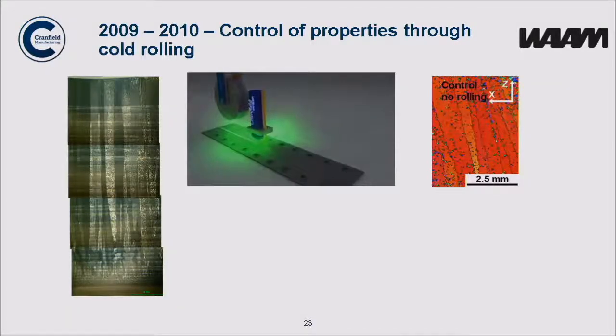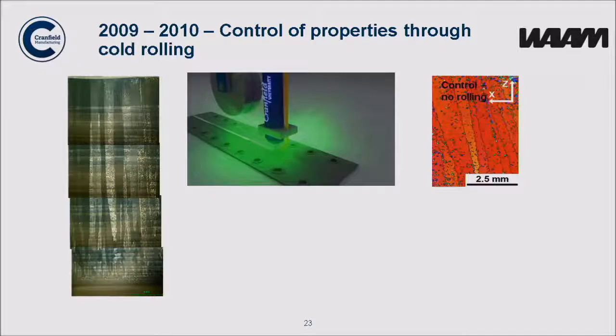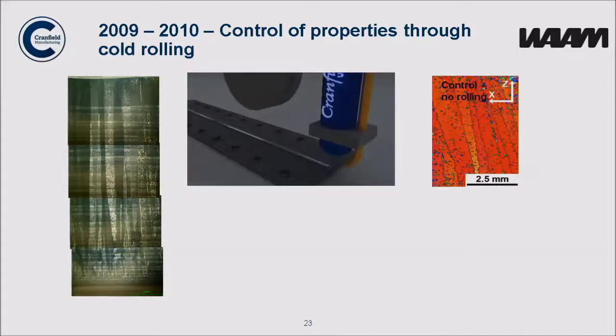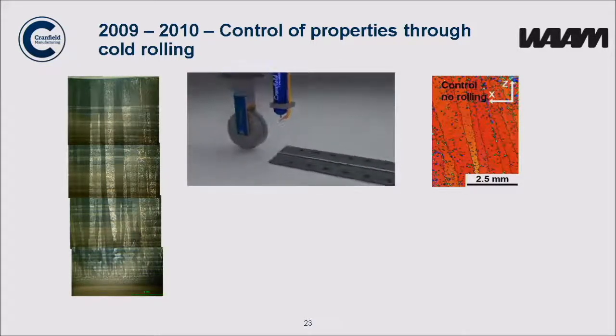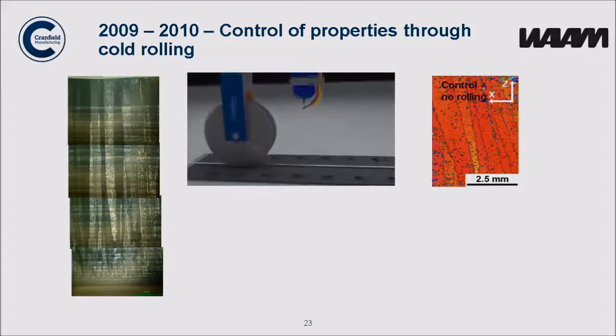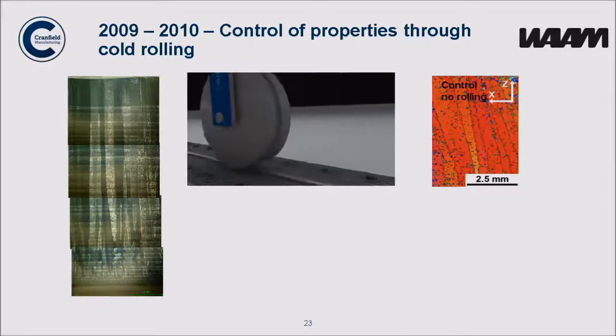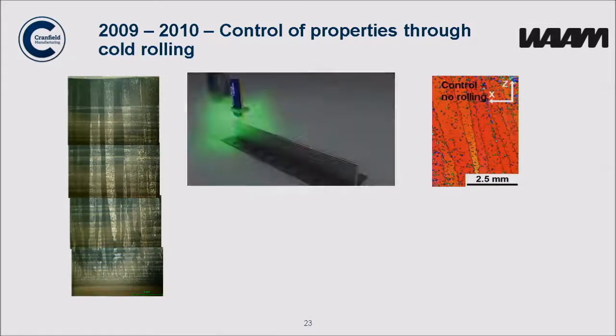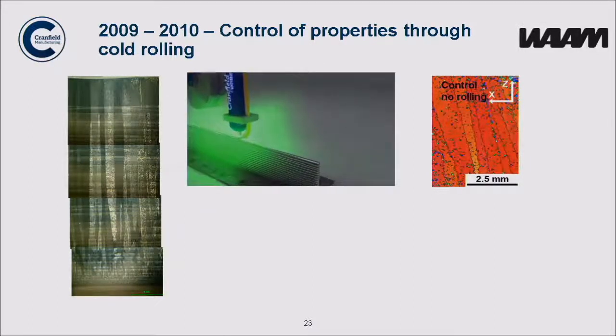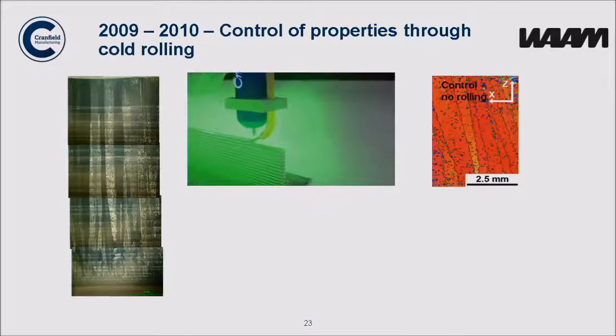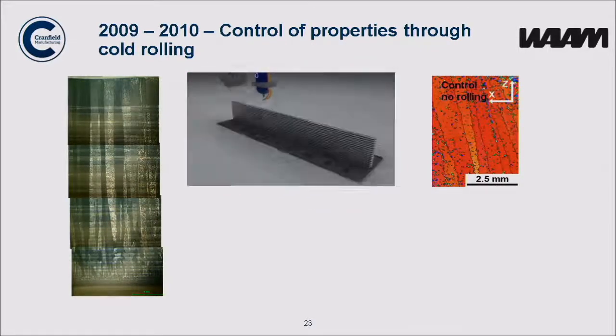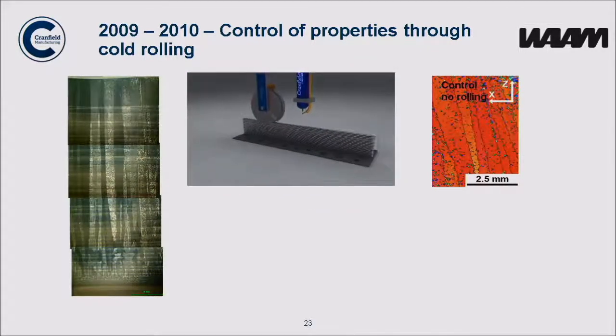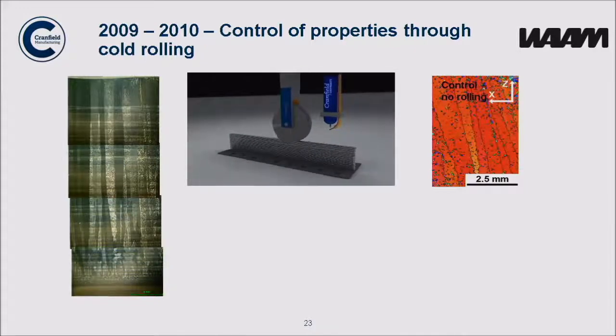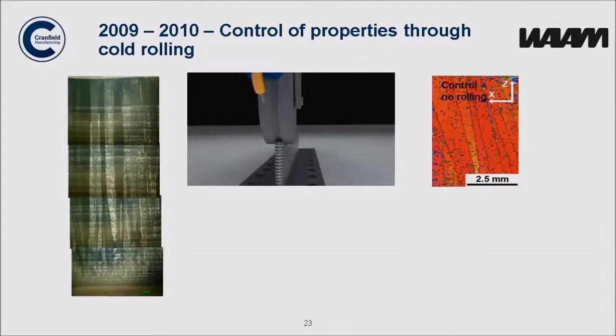Another factor that we introduced to improve the mechanical properties was cold work. This is a process that we patented, whereby we deposit a layer, we then cold work this layer using a roller in this case. We then put down another layer which thermally treats the cold worked material. And as was mentioned earlier, if you don't do anything in terms of titanium deposition, you get these large columnar prior beta grains. You get a very anisotropic structure which is highly textured.